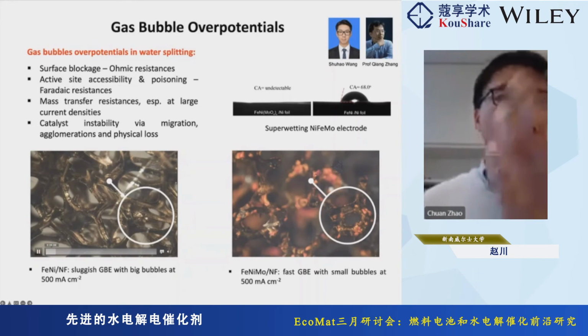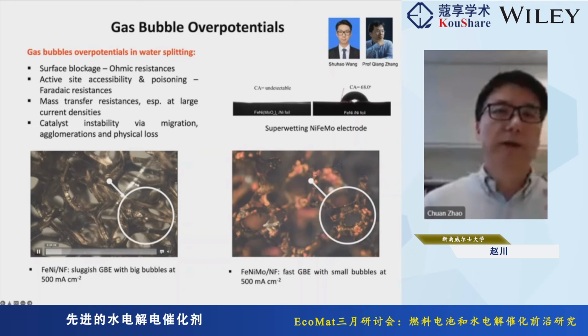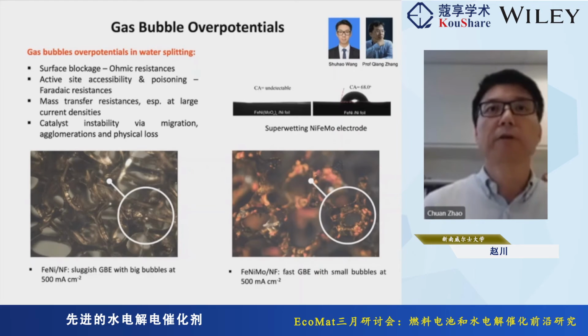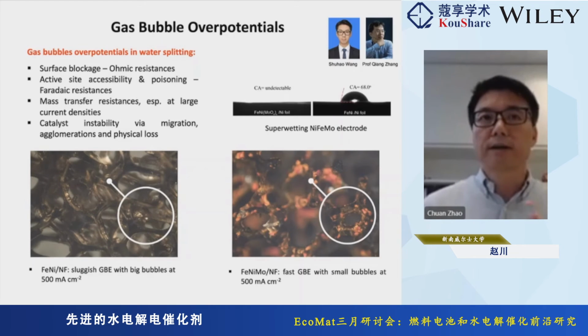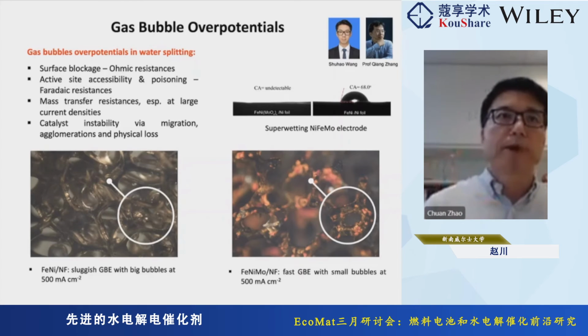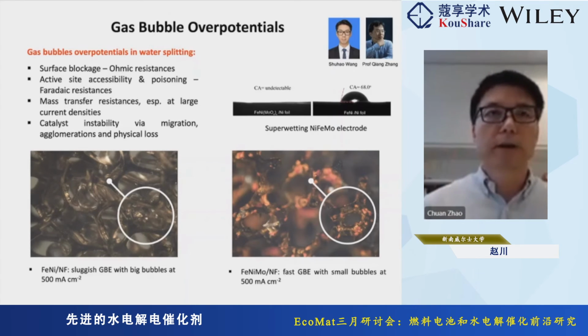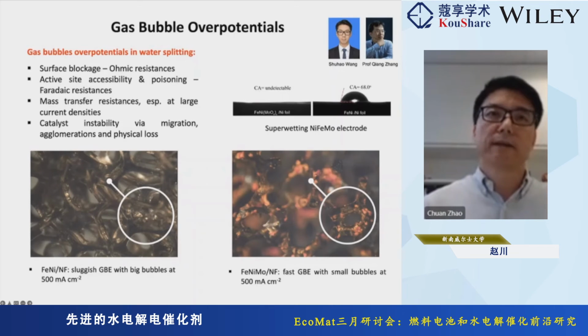So this is a typical nickel iron electrode where we apply a constant current of 500 milliampere per square centimeter. You can see the gas bubble evolution: very big gas bubbles evolve on the electrode surface and detach very slowly. So nickel iron is considered a very efficient catalyst, but we see quite significant gas bubble attachment on the electrode surface.